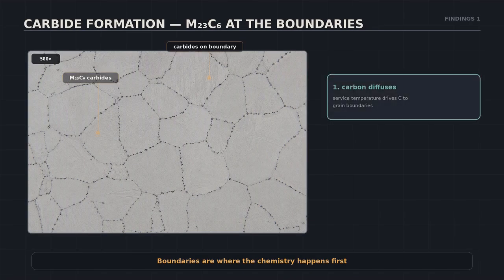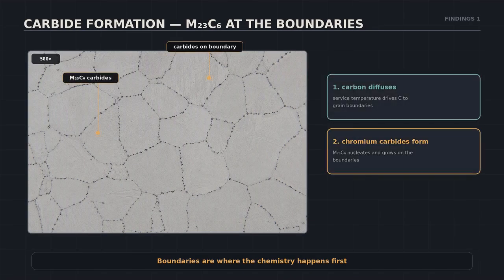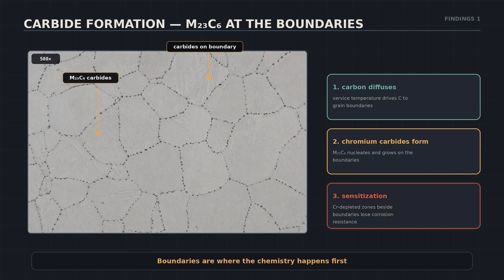Now the first finding, carbide formation. At service temperature, carbon diffuses through the steel and concentrates at the grain boundaries. There it meets chromium and forms M23C6 carbides, you can see them as dark particles decorating the boundaries. The price is sensitization, the zones beside the boundaries are drained of chromium and lose their corrosion resistance.